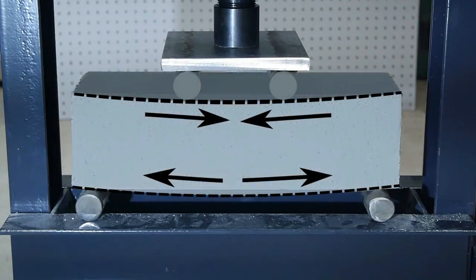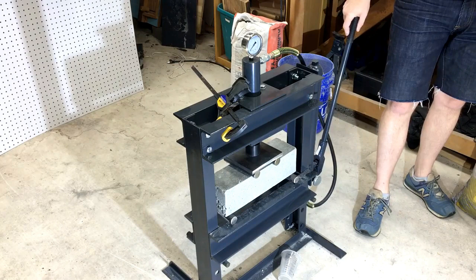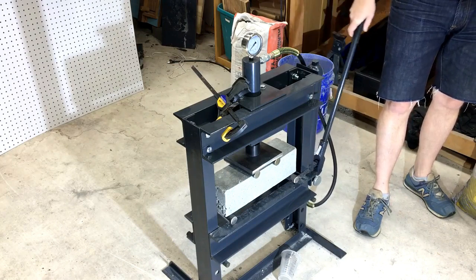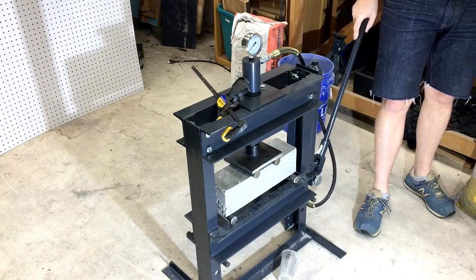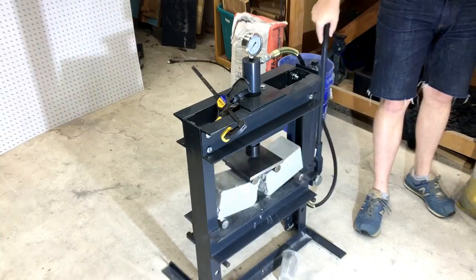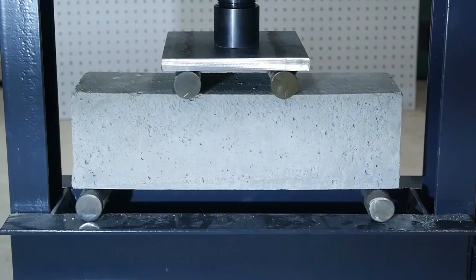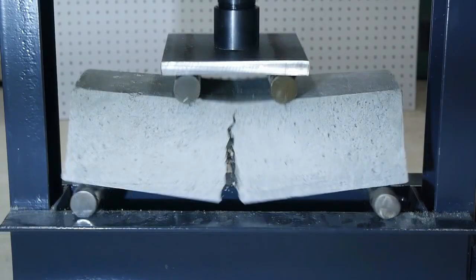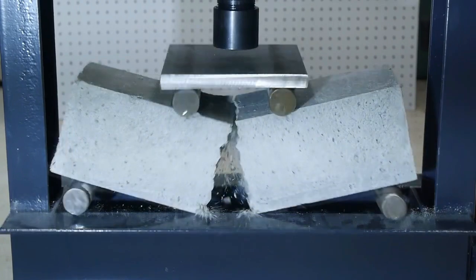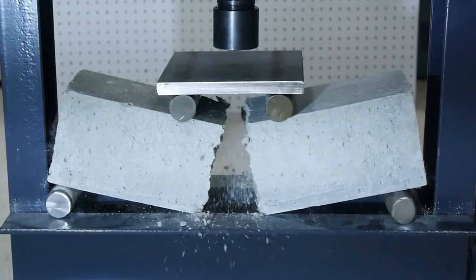The top of the beam experiences compressive stress, and the bottom of the beam experiences tensile stress. You can probably guess where the failure is going to occur on this concrete beam as I continue to increase the load. It happens almost instantly, but you can see that the crack forms on the bottom of the beam where tensile stress is highest and propagates upward until the beam fails.